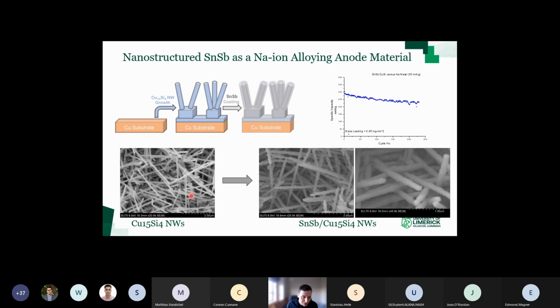So this is what the nanowires look like. They're conductive. He then coats them with tin and antimony. He evaporates on a bilayer, 20 nanometers of tin and 20 nanometers of antimony. He does that because they buffer each other. They sodiate, or alloy with sodium, at different potentials. So while there is a volume expansion, each material tends to buffer the other during their respective volume expansion. So you can get an increased capacity retention by doing so.